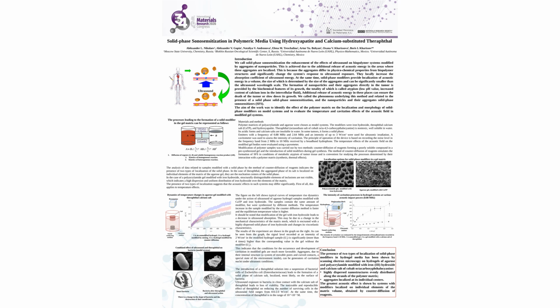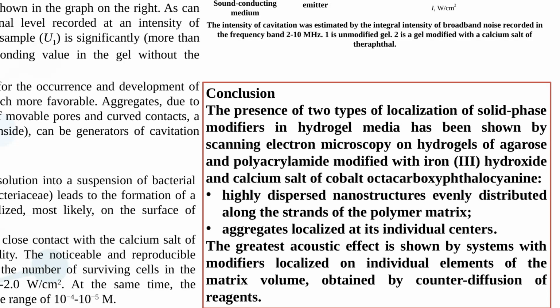The greatest acoustic effect was observed in systems where the modifiers were localized on individual elements of the matrix volume. These systems were obtained using the counter-diffusion method.